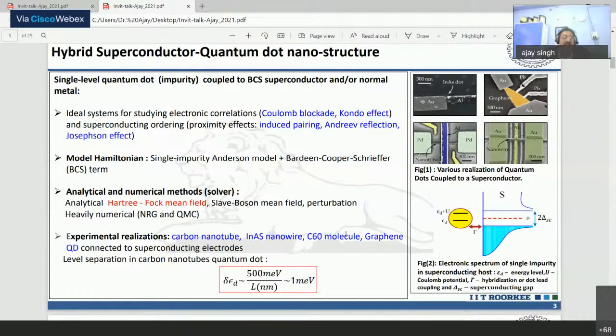If you look at such systems that are available, you have carbon nanotubes, nanowires, carbon-60. You can basically use these molecules and dots because the separation of their energy levels can be tuned to the level of, say, 1 milli-electron volt and less than 1, where you can take advantage of a superconducting order parameter, which is of some 0.5 or 0.2 milli-electron volt, and you can see the interaction of the dot level close to the Fermi level. So these are the realized systems, which can be thought of in terms of the energy level and Coulomb interaction, and a term which couples the energy level with the energy states of the superconducting lead and a superconducting order parameter.